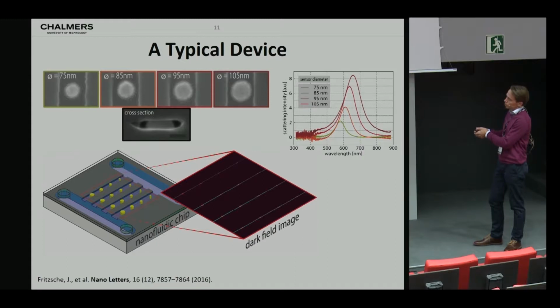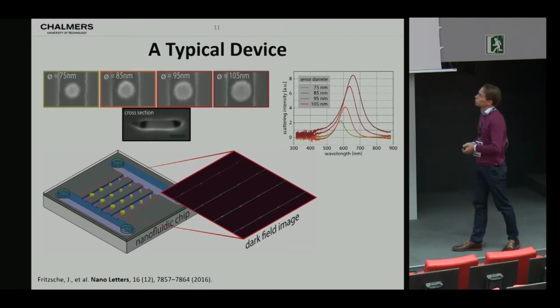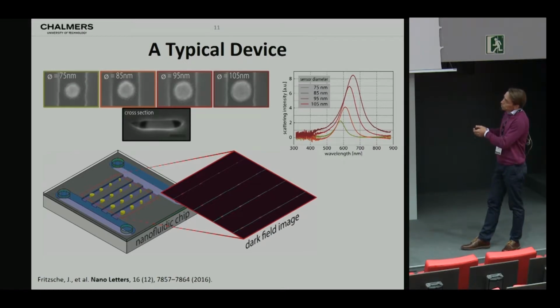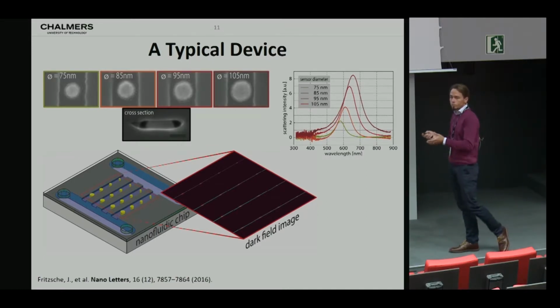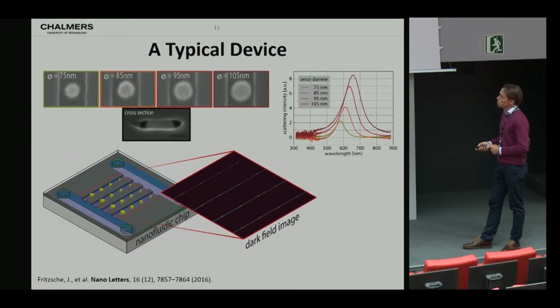In essence, it's comprised of two microfluidic systems connected by nanofluidic channels, which in turn are decorated by nanoparticles. This is how a dark field image looks. You can very nicely see the individual particles by the naked eye. Here we have again not taken any measures to suppress the scattering from the channel walls to make the channels actually visible. Then we can place nanoparticles of controlled size and also shape in these channels, and as you would expect on an open surface, if you increase the size of the particle, you will redshift your resonance. So nothing strange there just because we place them in these tiny structures.